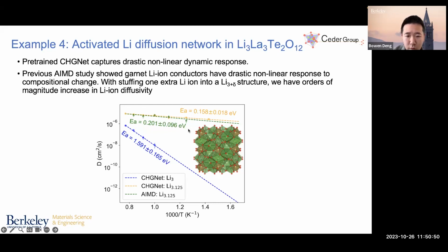And moreover, we were also able to simulate this blue curve, where we have a very high activation energy of more than 1 electron volt, which actually surprisingly matches very well with experimental values. But these types of dynamic process simulations with extremely high diffusion activation energies were not possible with AIMD, because these ion hops are rare events to be sampled. Essentially, AIMD cannot reach the timescale that is required for these types of simulation.